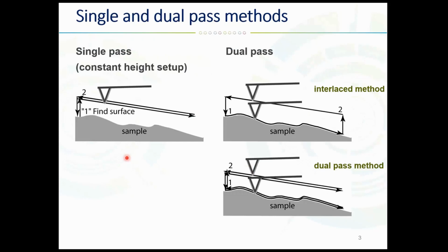And the lifting can be done in so-called single or interlaced and dual scanline modes. So on the left-hand side here is a single pass, like a group of single pass methods or constant height setup. When the slope of the surface is measured from a completed topography image or line before the imaging of the long-range interaction is started. And so we go one time across the sample, then we lift, and then the tip is scanned at fixed height above the sample, compensating the average slope going backwards.